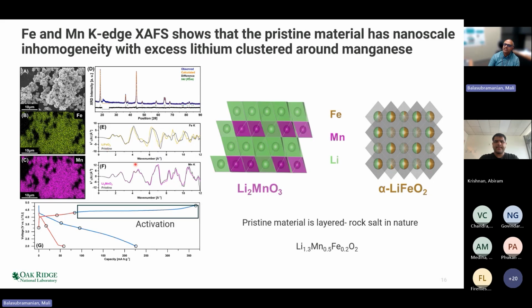Now you can take this material and perform electrochemistry, and you see that in this region, which is marked by red, you expect the normal electrochemistry, which involves the cations. And then during this region, it is called the activation, where it is expected that something beyond the cation contributes to charge compensation, and it is normally considered to be oxygen activation. Exactly how this process takes place is something which has been debated and studied in the literature for over two decades. Now we're going to follow this from the iron and manganese viewpoint. How does the oxidation state and structure change using XAS and X-ray emission spectroscopy?